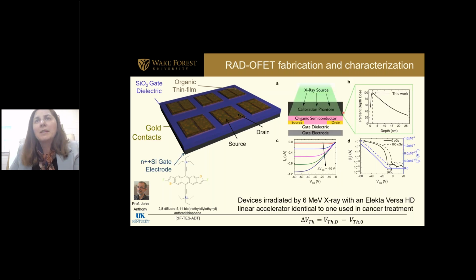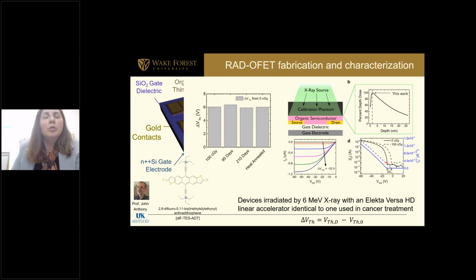You see here, we place them under the X-ray source, and then we can control the dose. And you see here that we have a shift in these current voltage characteristics, but now this shift comes solely from exposure to radiation. And we use this shift in the threshold voltage, VTH, as a measure of the response to radiation. And we can do that because this shift persists even after 95 days, 210 days, even after heat annealing. So it's quite stable, which allows us to come back to the lab and measure the shift and do statistics.